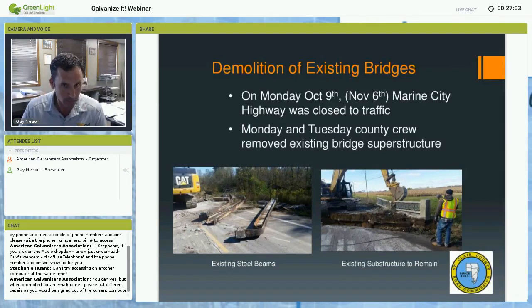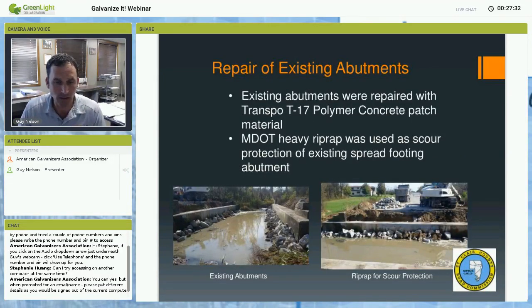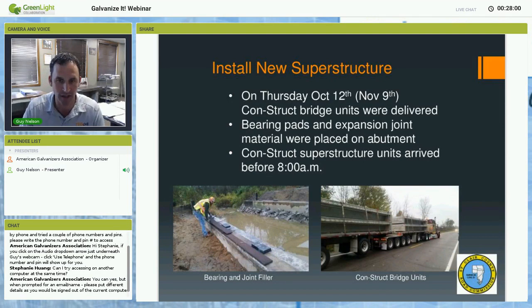So we started demolition, as you see here, on October 9th of Bridge 408, which is the 25-foot span, 90-degree bridge. Bridge 409 was started about a month later, after 408 was installed. County crews came out and in 2 days removed the existing superstructure. Once it was removed, they placed riprap for scour protection in front of the abutments and patched any problem areas on the existing abutments. We used a T17 polymer concrete by Transpo Industries, and you'll see later we also use that for deck joints. So the first thing was repairing the abutments and placing riprap.